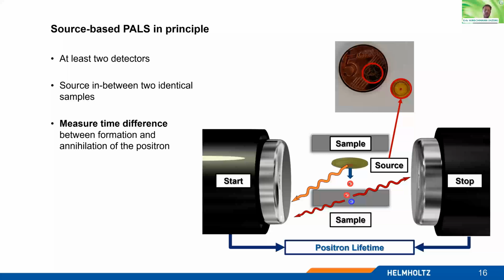And luckily, the sodium-22 delivers, besides the positron, also a 1275 kiloelectron volt start signal. So you measure the time difference between the start signal and the stop signal from the annihilation event, and then you get the positron lifetime and all the parameters I mentioned before.